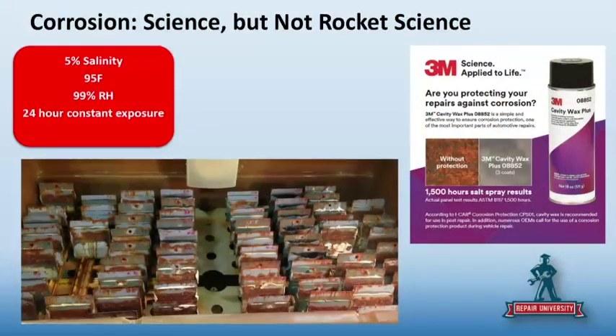So, Shawn, tell us why cavity wax is so critical. Well, in my opinion, it's one of the most important steps as far as corrosion protection goes, because in a lot of cases we're in blind cavities, and the area where it's most critical is welded on panels. Any welded on panel, you have burnt the coatings away inside the flange, and you need to use cavity wax to allow it to creep in and protect those welded areas.